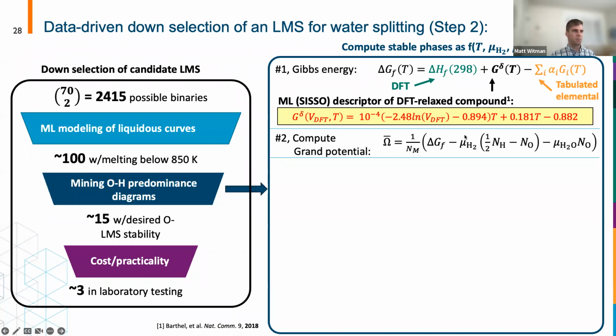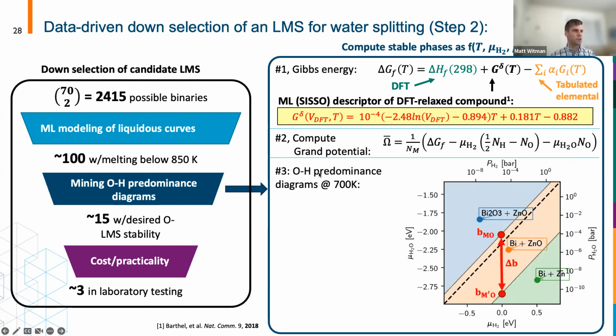So in the system, we're open to oxygen and hydrogen atoms, but I've rearranged that expression based on the chemical equilibrium expression for water to re-express this in terms of control variables that we actually control in the lab, which are chemical potential of hydrogen gas and chemical potential of the water gas. And once we do that, we can construct these OH predominance diagrams in high throughput. So construct the phases that minimize this grand potential. And you can see here, we are plotting the stable phases as a function of now things we control in lab, the hydrogen chemical potential and the water chemical potential. And if you assume they're ideal gases, you can map that to the partial pressures you see here.